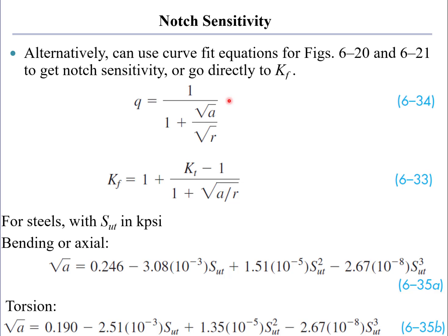So the easier thing to do, instead of reading off of a chart, is to use an equation to calculate what the notch sensitivity is. And it turns out a huge amount of research was done in the material science community, and this is the Neuber relationship, where you can calculate the notch sensitivity by taking 1 over 1 plus the square root of A divided by the square root of R, where R is the fillet radius of interest, and A is a material length scale that depends upon the material.